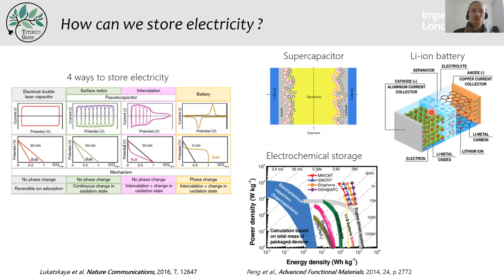In the case of the lithium ion battery, you're probably aware, you have intercalation. So the charges, in this case lithium, diffuse inside the material on the anode, usually graphite, and on the cathode, for example, lithium cobalt oxide. And this intercalation induces a phase change, and that is observable either on the plateau of the galvanostatic charge discharge or on the peak of the CV. And of course, the fact that the charges intercalate means that you can store much more energy, so batteries have high energy density. Here you can see on the Ragone plot on the bottom right, the batteries have energy densities between 100 to several hundreds of watt-hour per kilogram, whereas electrochemical capacitors have much lower energy densities, usually 5 watt-hour per kilogram, but much higher power density because the kinetics of this ion surface sorption is much faster than the intercalation of the ions inside the material.